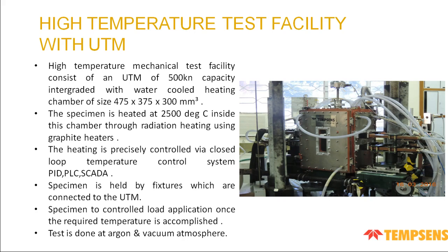Now this is a very special furnace designed for a high temperature test facility with UTM. So the high temperature mechanical test facility consists of a UTM of 500 kilonewton capacity integrated with a water cooled heating chamber of size 475 by 375 by 300 mm cube.